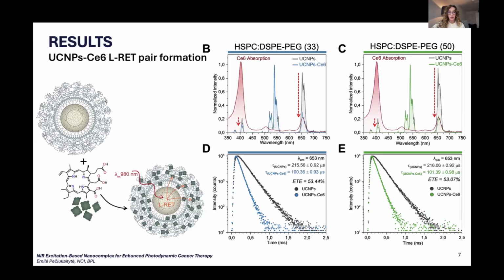So we performed time-resolved luminescence measurements, which are considered to be definite evidence. While the average decay time of upconverting nanoparticles alone was approximately 215 microseconds, it decreased to around 100 microseconds upon nanocomplex formation. Importantly, PEG density did not significantly influence this result, and both formulations showed approximately 53% energy transfer efficiency.